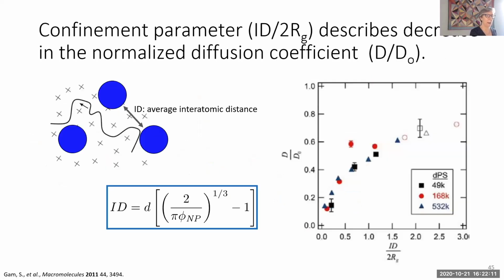We developed this idea of a confinement parameter back in 2011 with this first set of data. And so again, the interparticle distance is the surface to surface particle separation. And you can calculate that using this expression, which is the diameter of the particle and the concentration of the particles, assuming you have them well dispersed. And now we can see that this is the normalized diffusion coefficient relative to the bulk as a function of this confinement parameter. And we can see that independent of the molecular weight of the polymer, we get really nice collapse for these three sets of polymers.